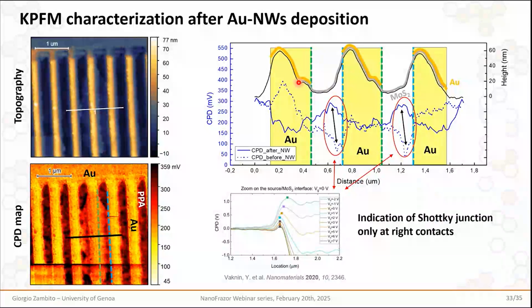And this is clearer if we compare line profiles. Here in this graph, we compare the topography line profiles, but also the CPD line profiles extracted from this image after gold nanowire deposition, represented by this solid blue line, and the same CPD line profile acquired before nanowire deposition. You can see that we can distinguish between two behaviors. Left-type contacts, indicated here by the green dashed line, present absolutely no change in CPD values before and after nanowire deposition. This indicates that we have reached a match between the work function of gold and of MoS2, which results in the creation of an ohmic, good quality contact.